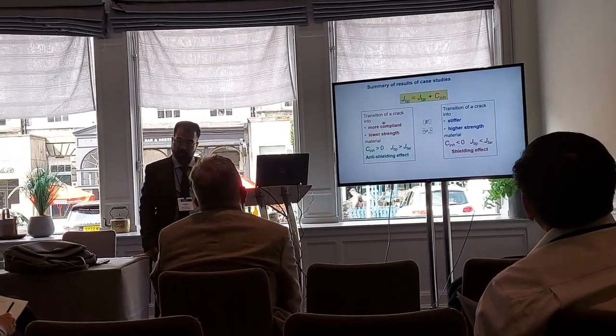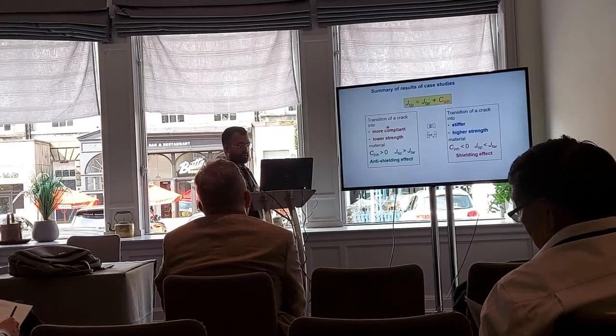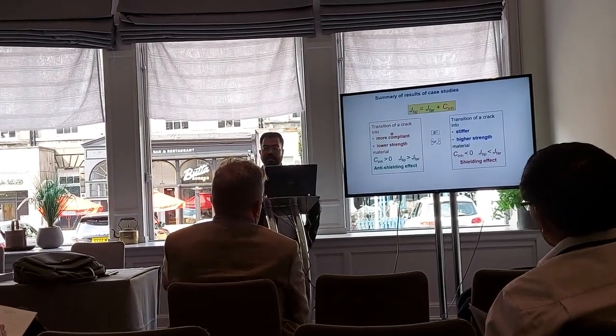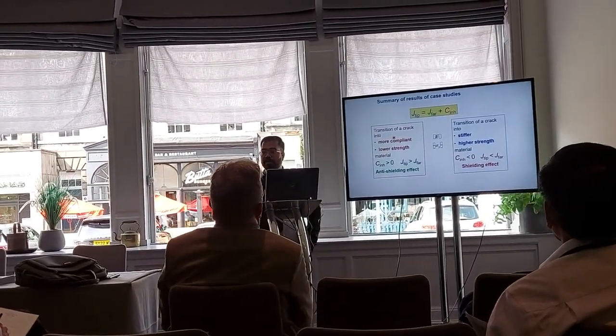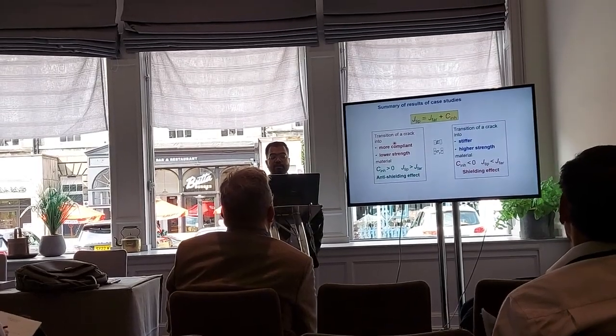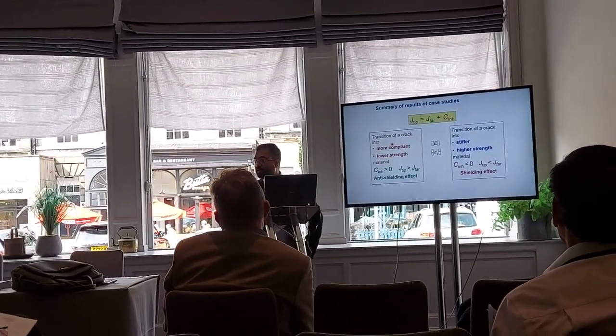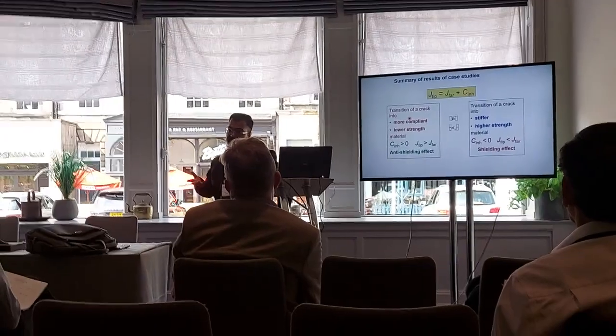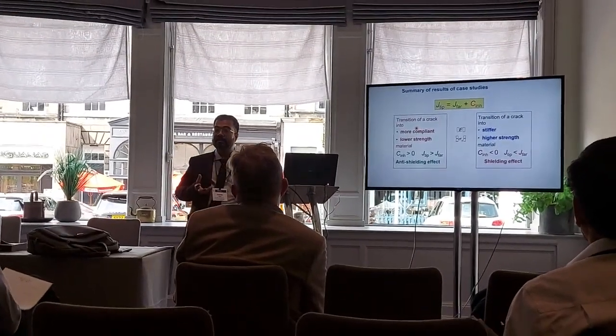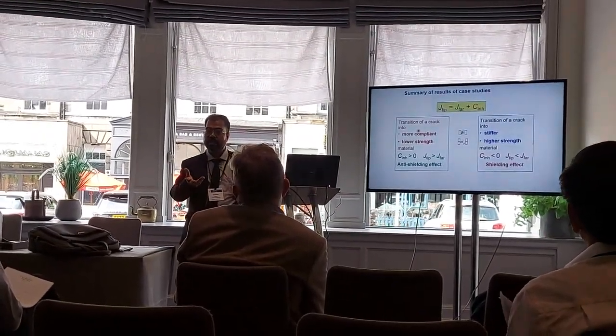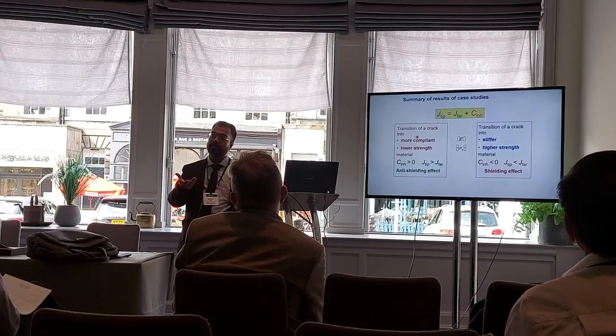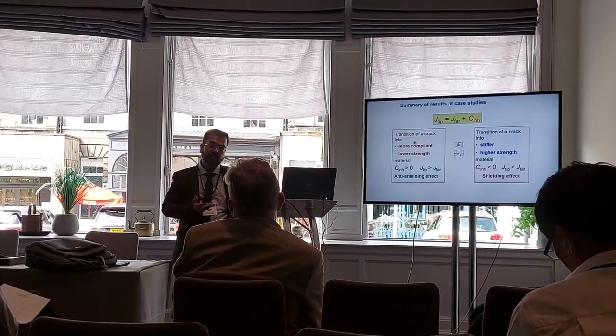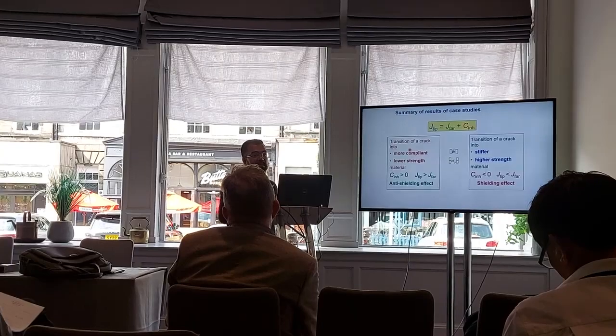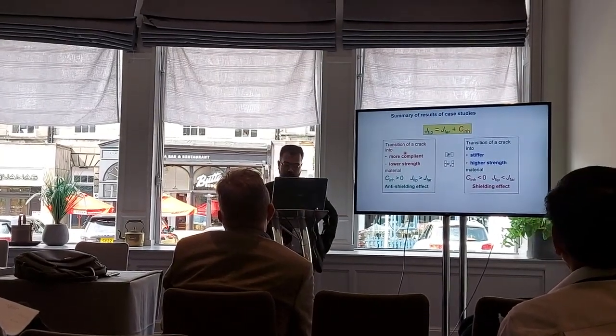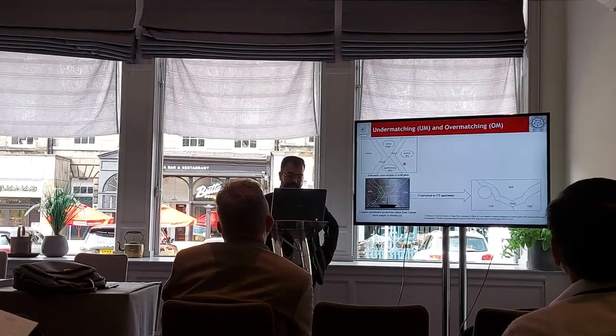reference configuration. So this extra term, if it is negative, so if the C inhomogeneity term is negative, that means you have less energy available than what you are supplying in terms of J-far. So the crack will have a tendency not to grow as fast as it could, and the opposite will happen. If C inhomogeneity is higher, in that case J-tip will be higher, and the crack will have a higher tendency to grow. We'll see why that happens.